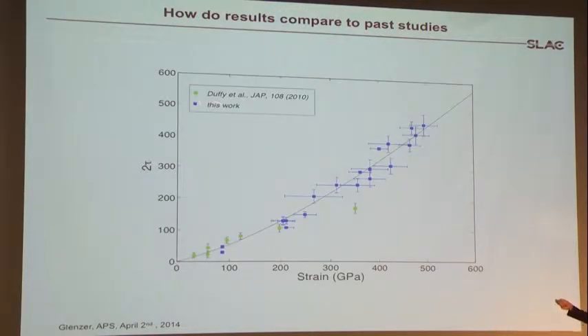And when you compare this to previous work in diamond anvil cells, where people have measured strength before, we actually make very nice contact down here at the 2 megabar regime, but we can push it now all the way out to 5 megabar. So even at 5 megabar, there's just no indication that the diamond has lost its strength yet. Of course, this was not known until we did these measurements, and we would like to push this further and find out at what point diamond will lose its strength.